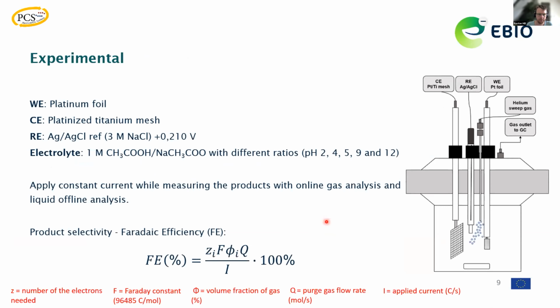So let's see. Before I really show our experimental results, I would also like to quickly address what kind of electrochemical cell we have been using. It was quite a poor man's electrochemical cell, meaning a batch reactor, where we used a platinum foil working electrode, and we also used a platinized titanium mesh as a counter electrode. The reference electrode, of course, enabled us to really understand what the potential of the working electrode is. We started off with different electrolytes containing mixtures of acetic acid and acetate, and we adjusted the pH of the electrolyte to the pHs as indicated here on the slide.